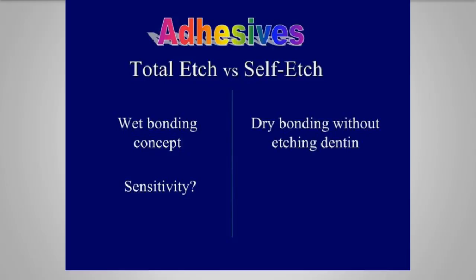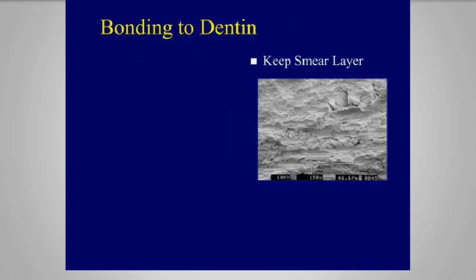That sort of thing. Or with the self-adhesives today, we have dry bonding without etching the dentin. We actually have an acidic monomer that changes the pH to a neutral pH to cause resin tag formation, and we have less sensitivity. However, the caveat is we have poor enamel bonding according to the literature, unless you rotary abrade the enamel and or use phosphoric acid, called selective etching, which is my protocol to do.